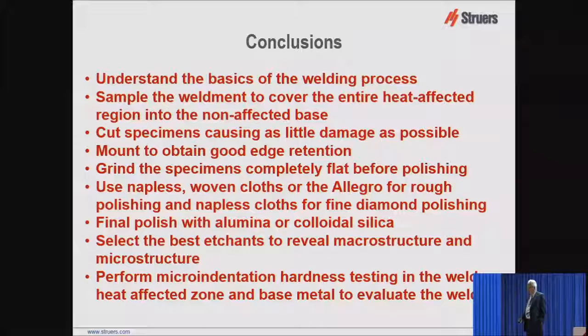If you want to look at the edge, you've got to mount the sample. Because if you have an unmounted sample, when you press the sample down against the surface, whether it's grinding or polishing, you're going to have a flow with the material that's rubbing against the sample, and you're going to round off every edge. You're never going to be able to see the true edge and see what structure is there. And if you want to have good edge retention, you have to use the right mounting compound also. And in a few cases, it might be very helpful to electroless nickel plate it if it's a sample that can be electroless nickel plated, because not all material can be. So we want to grind the specimen completely flat before we start polishing,